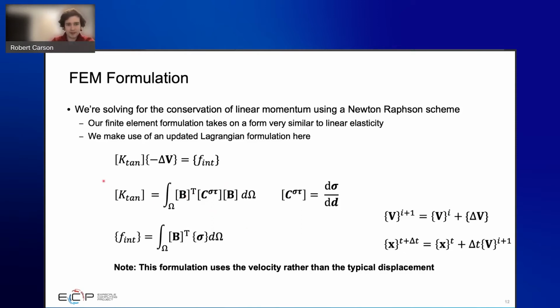Except that in the tangent stiffness matrix, instead of having your elasticity tensor here, our material tangent stiffness matrix is the derivative of our stress with respect to our deformation rate. And our deformation rate is just the symmetric portion of our velocity gradient. I mentioned earlier that we're making use of an updated Lagrangian formulation. What this means is that our mesh nodes are always in the current configuration. Because of this, we want our primal variable that we're solving for to be the velocity field rather than displacement. This is a slight variation, but it's mainly due to the fact that for our kinematics, it's a lot easier to describe things with the velocity field rather than the displacement field.